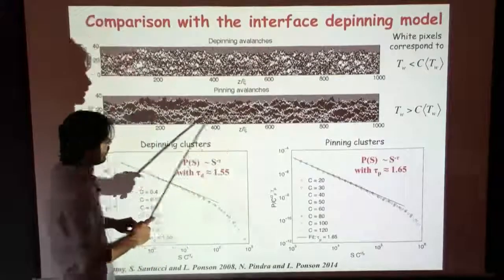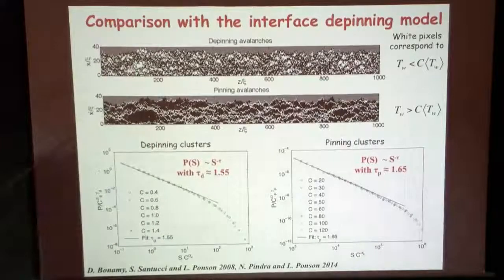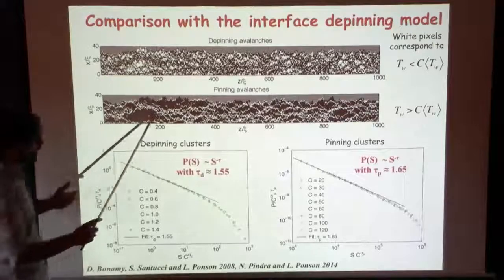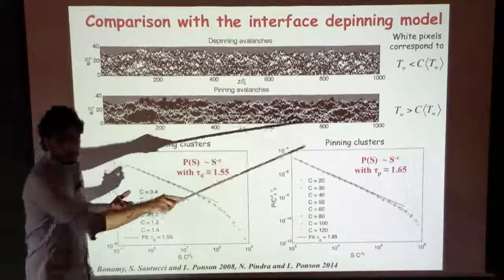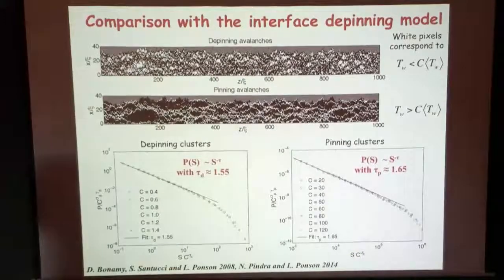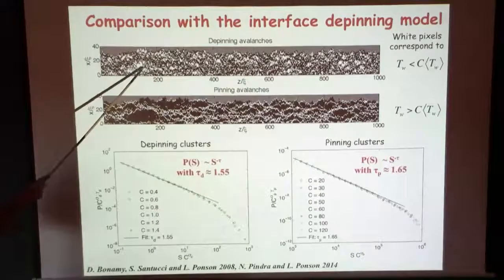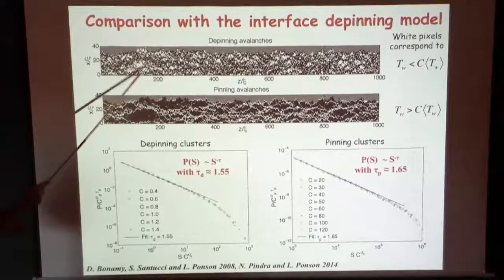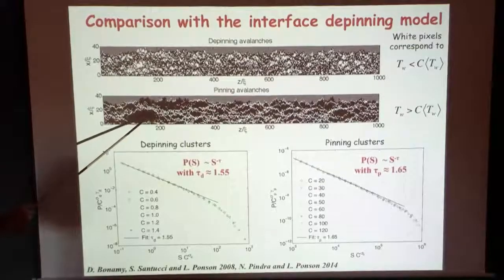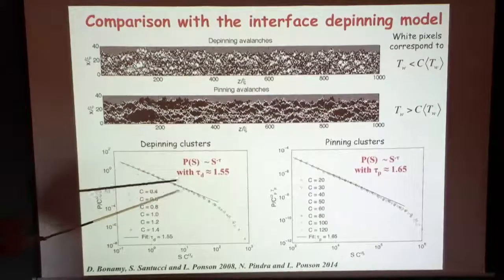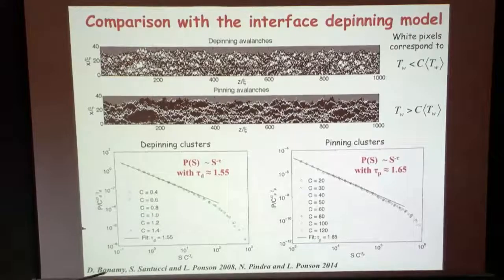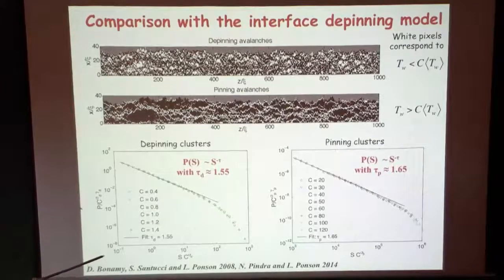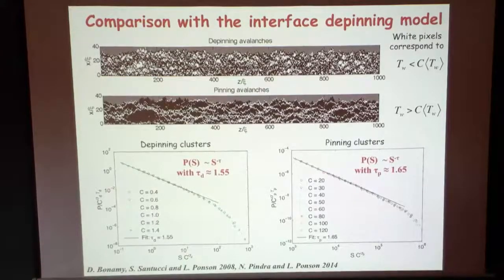You can also define pinning avalanches. Here, the white regions are the regions where the front has spent an abnormally large amount of time, and you see lines corresponding to pinned configurations. You can play the same game, analyze the statistics of the size of these clusters, and rationalize the value found in the experiment with the non-local model.